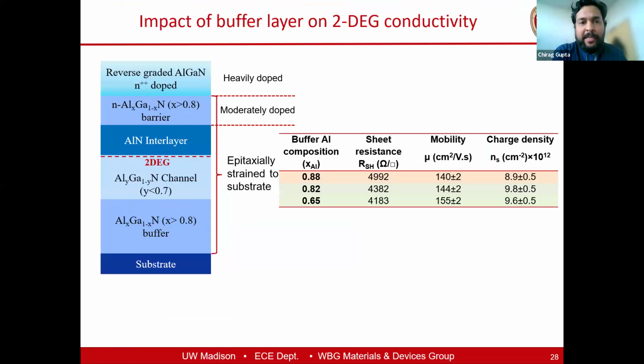So what we have done is we have really tried to dig deeper into this design, basically to look at how this design can be tuned to give what we want. So we have studied the buffer design. Depending on what kind of buffer you have, if you carefully design your buffer, control the alloy composition well, then it can give you a little bit of boost in mobility. You can see it's going from 140 to 155, not a significant boost. But overall, in your sheet resistance, which is what you care about from a conductivity viewpoint, you do get some advantage if you design your buffer carefully.